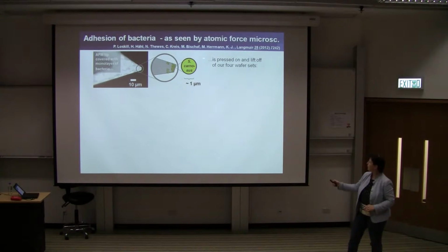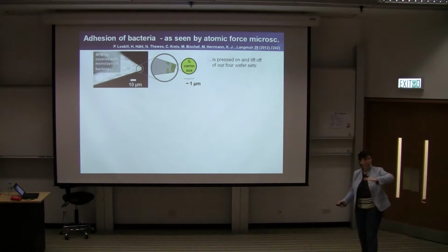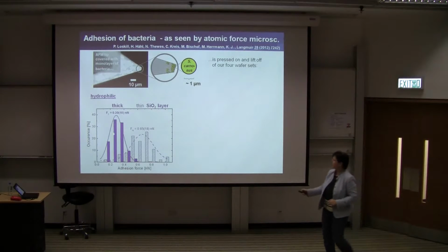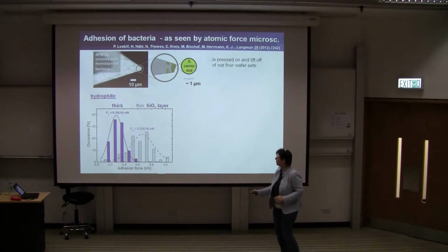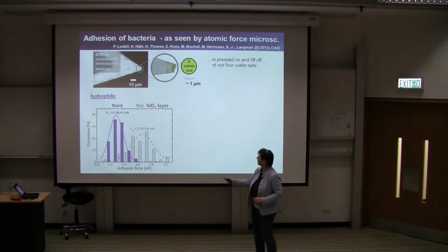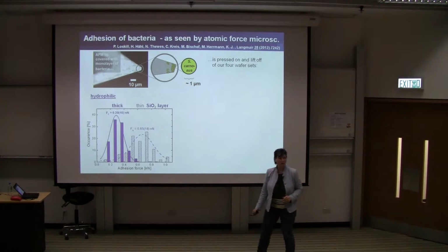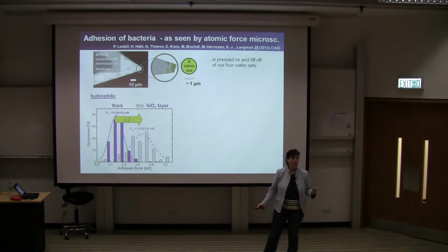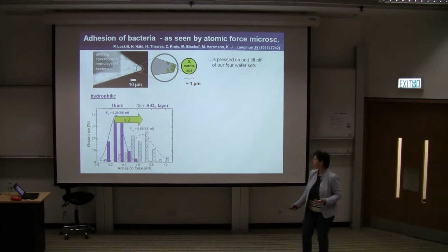Now we have our seeded wafer and press it on and lift it off of our 4 different types of wafers. Now let's first look at the hydrophilic wafers. Here is the occurrence of a certain adhesion force for the thick silicon dioxide, and here it is for the thin silicon dioxide. And as before, on the thick silicon dioxide, we record lower adhesion forces as compared to the thin silicon dioxide. So reading publications of different groups from different continents using different silicon wafers, there can be a difference of a factor of 2 just because the silicon dioxide layer hasn't been recorded.